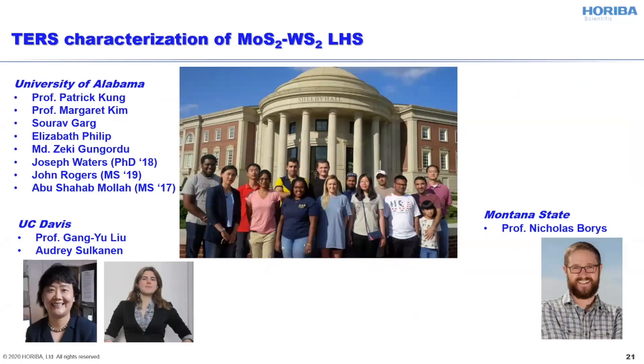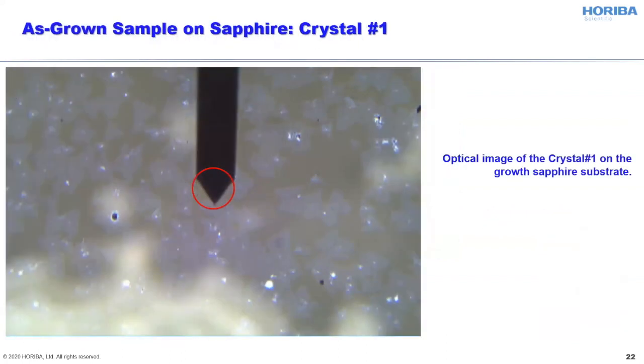And following, I will present the results of TERS and PL characterization of molybdenum disulfide and tungsten disulfide lateral heterostructures that we did in collaboration with three different groups: a group of Patrick Kung at the University of Alabama, UC Davis, Professor Gang-Yu Liu, and our good friend Nicholas Borys, who is now at Montana State University. So these crystals with a molybdenum disulfide core and tungsten disulfide shell were synthesized on a sapphire substrate. And here you can see an optical image of these crystals and the image of the cantilever positioned over the crystal that we will be mostly talking about in the further presentation.